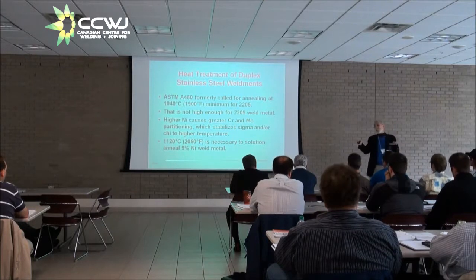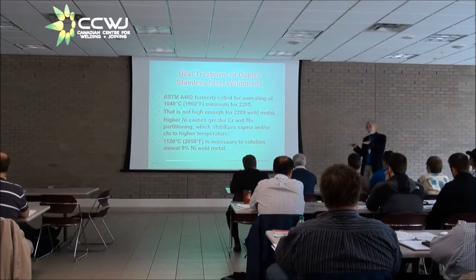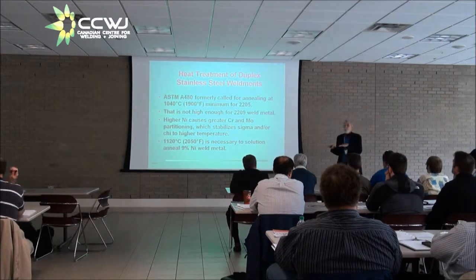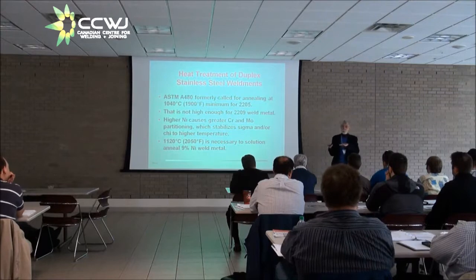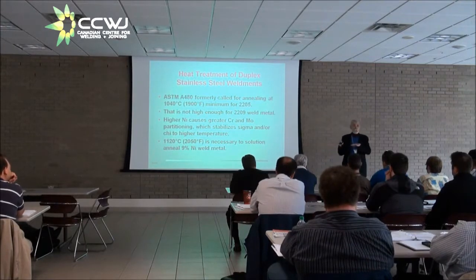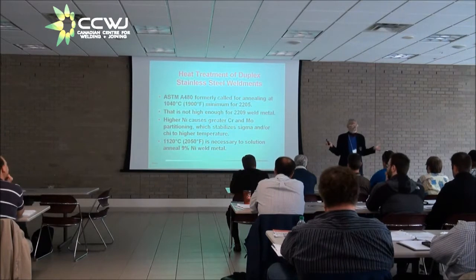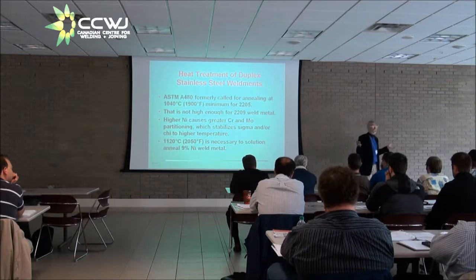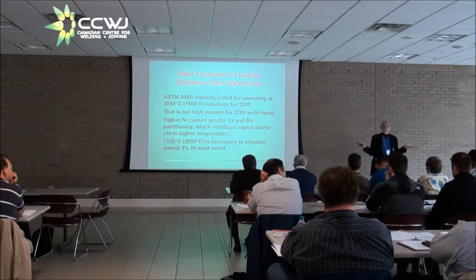So they put it back in the forming press, and they were just going to give it a little bit of a nudge to true it up, and it fractured. The welds unzipped. They literally unzipped, and the plates came apart. They investigated and found that the weld metal was loaded with sigma phase.